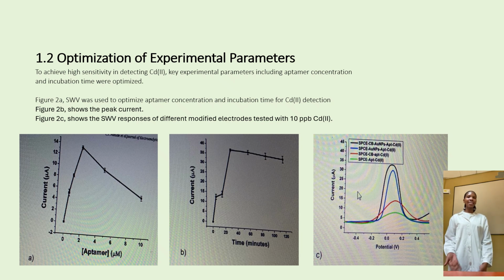In figure A, SWV was used to optimize aptamer concentration and incubation time for cadmium detection, where the current response increased as aptamer concentration reached a maximum of 2 micromolar, after which it decreased due to overcrowding on the electrode surface. Figure B shows the peak current increased up to 30 minutes, as you can see on figure B, then slightly decreased beyond that. Therefore, 30 minutes was chosen as the optimal incubation time.